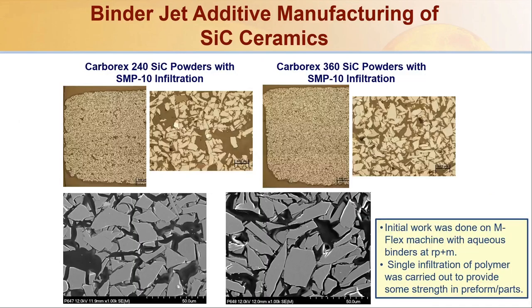mix. So when we started this work about 6-7 years ago, for the first time, we were basically using some very irregularly shaped silicon carbide powders. They were basically the Carborex powders. And you see here some of the microstructures of those powders and powder shapes and sizes. And actually, we used to also infiltrate these preforms with the SMP-10, which is the pre-ceramic polymer, just to provide a little strength. So this is not the densified material, but it is basically to provide some strength so that parts can be moved from one facility to the other facility.